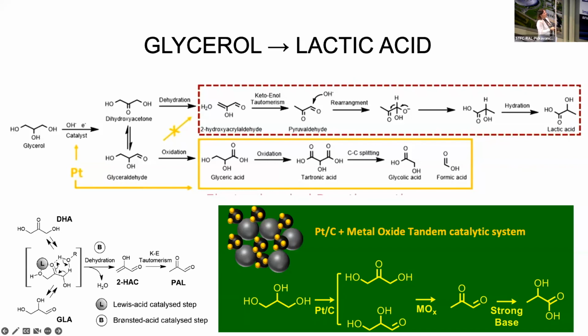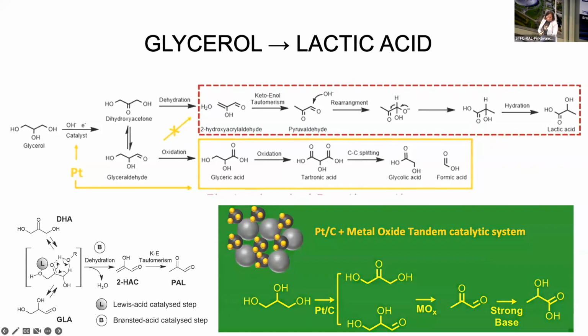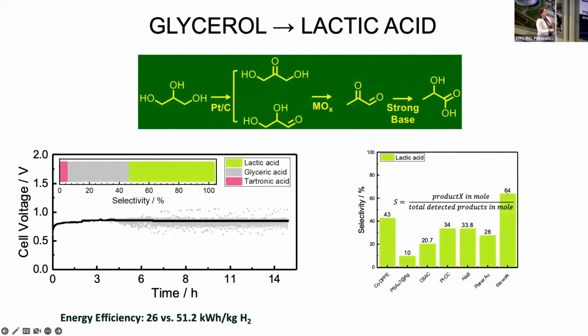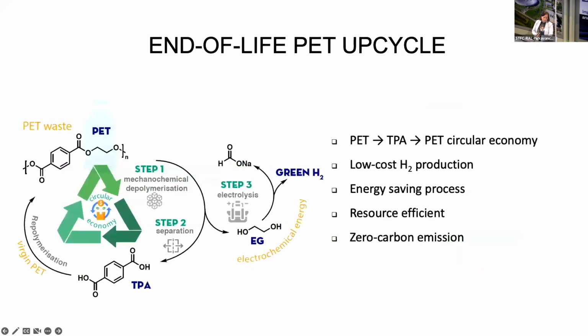But basically, we put platinum on something that has a lot of Lewis acid groups, and indeed platinum does this step, and in combination with the Lewis acid groups does the next step, and then in solution you get lactic acid. We got very nice results in the sense that we got the highest selectivity in the literature for an electrocatalysis process to lactic acid from glycerol. And of course, hydrogen evolution is happening, with much higher efficiency overall because the lactic acid formation happens at low potentials.